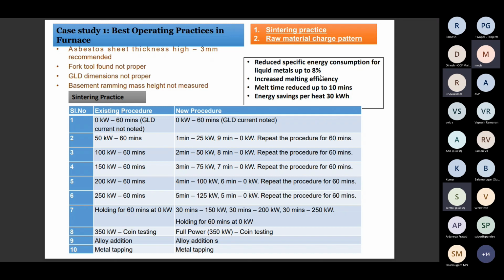These best operating practices reduce the specific energy consumption for liquid metal by up to 8%, increase the melting efficiency, and reduce the melt time by up to 10 minutes. Energy saving per heat is approximately 30 kilowatt-hours. In the existing practice, they followed this step: 0 kilowatt for 60 minutes, and the GLD current is not noted. The new procedure is 0 kilowatt for 60 minutes, and the GLD current is noted regularly.